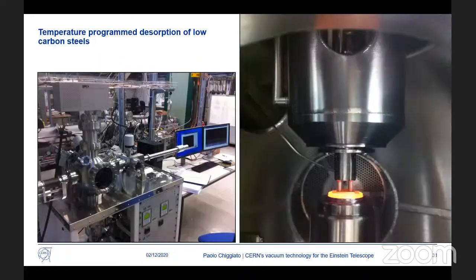So we started just a few months ago, and we bought some selected steels that have good properties for welding, weldability, and also for other purposes, and a limited cost. We started by using small samples. You see this yellow one, a hot sample during heating. The first measurement is the temperature programmed desorption, in which the sample is heated progressively and uniformly to high temperature, and we measure by quantitative gas analysis the gas coming out from the sample.